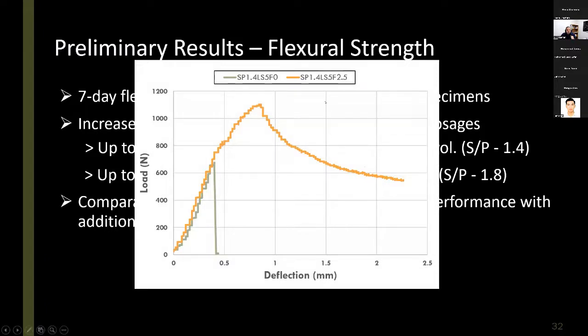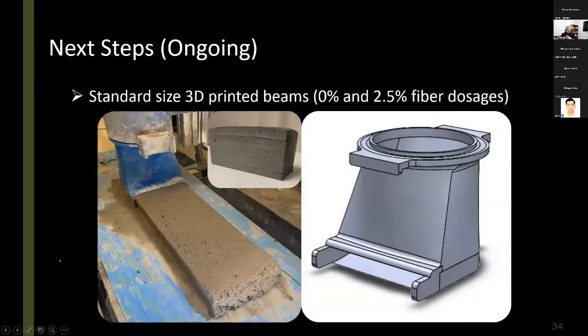The orange graph is showing a mixture with 2.5% fiber, the green one with no fiber. And as you can see, not only are we getting improvements in the flexural strength, but also the ductility of these materials, which is a very important factor in the tensile performance of construction materials, are being improved as a result of steel fiber inclusion at high dosages.